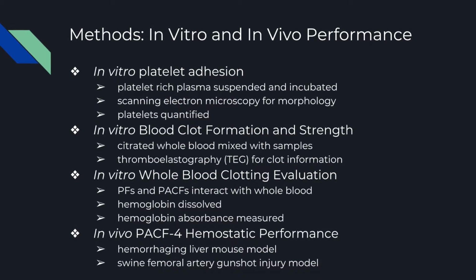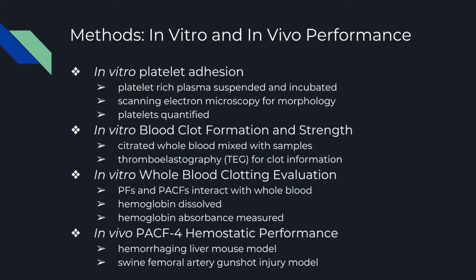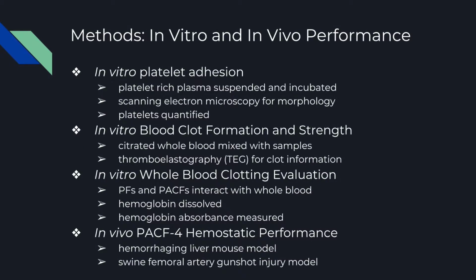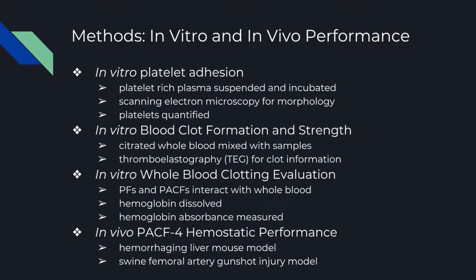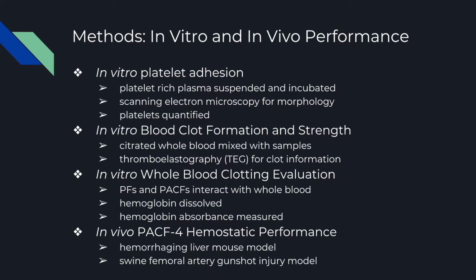In the gunshot model, the vessel bled freely for 30 seconds. Then PACF particles were applied quickly and as thoroughly as needed to stop the bleeding. The injury was observed every 10 seconds, and the hemostatic time was recorded. The blood flow, blood vessels, and morphology of the samples were computer monitored.